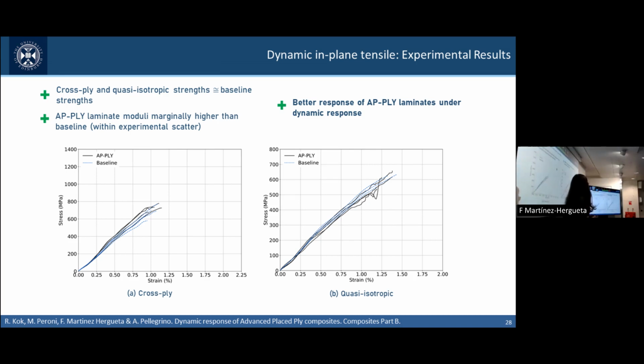So the first finding, when we compare the AP-PLY laminates with the baseline laminates, these are again the cross-ply and quasi-isotropic laminates that we have shown before. They just have higher thickness, but it's the same structure. We can appreciate how stiffness is still looking the same. There's no difference in stiffness between the AP-PLY and the baseline configuration. But very interestingly, in both laminates, cross-ply and quasi-isotropic, we find the same strength. So that means that basically the detrimental impact of the undulations that we appreciated in the quasi-static regime is not as relevant for the dynamic regime.